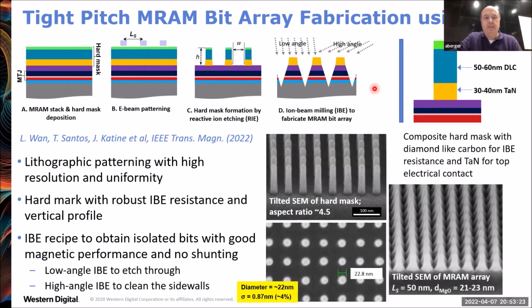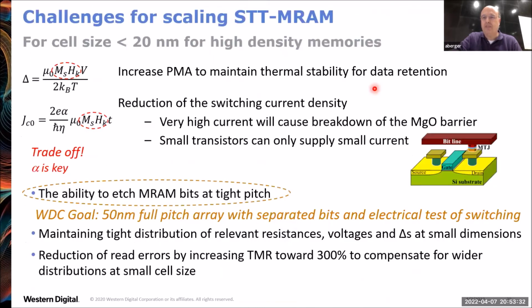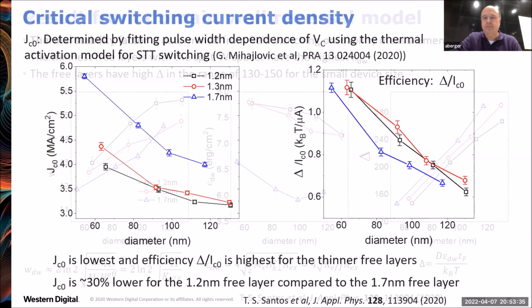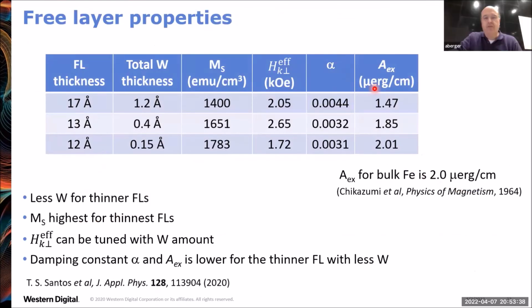I thought the thickness, if I saw this correctly, for the tungsten that you're using was 0.15 angstrom. So this is 5% of a monolayer, right? Yes. I was wondering, of course, this is the large area average there. But wouldn't that be a big problem in scaling the technology? Because if you make it smaller and smaller, then the variability of how much tungsten you get in every device will vary very significantly in terms of its relative contribution. So I was wondering if you could comment on that.